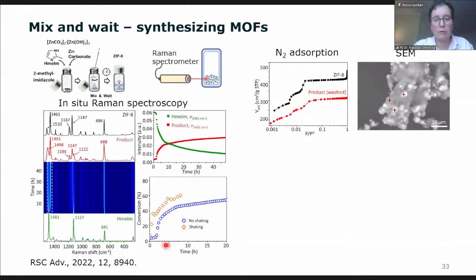of product. We then look more closely into the process, and you can see here what happens if you don't shake the vessel at all, just mix it and let it rest. So you can see we end up with a conversion of around about 50%. If you shake at the beginning, then you can see that the conversion is faster and reaches around about 60%, and it gets even better when you add a bit of water to the process. You see the data here. If you add water and let it rest, then we end up with something like 77% conversion. And here, if we add water and mix it, then you have a faster process, also leading to a conversion of about 77%.